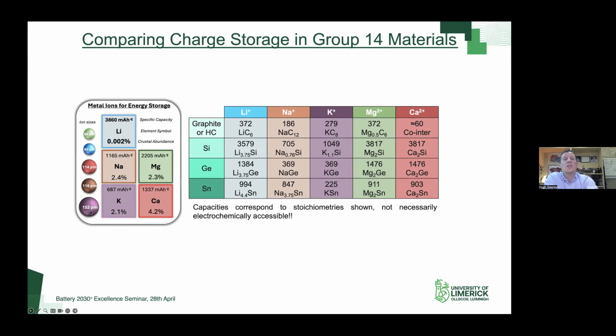Okay, so the charge storage mechanisms that we can unlock will be very much linked to the charge carrier size, firstly. If we look at this table here, this is to be taken intentionally with a pinch of salt. I mention this as a caveat that the capacities that I show up here, they're all in terms of milliamp hours per gram. They are based on the phases that are shown below. So in this case, some of these are not easily accessible or may not be accessible at all. So if I flag this sodium silicon system here, you'll see that the theoretical capacity, which would be quoted in any number of papers, is linked to the formation of this specific Na0.76Si phase.